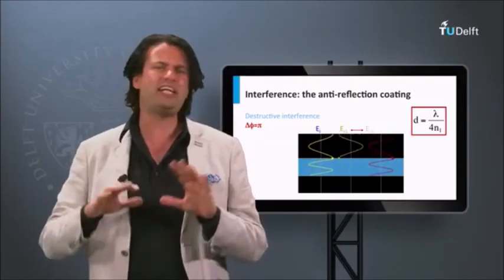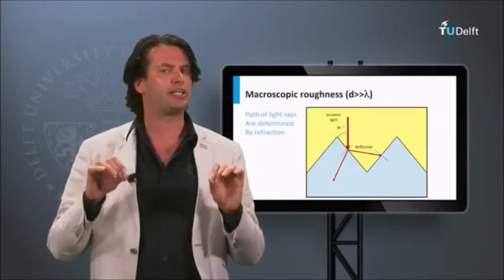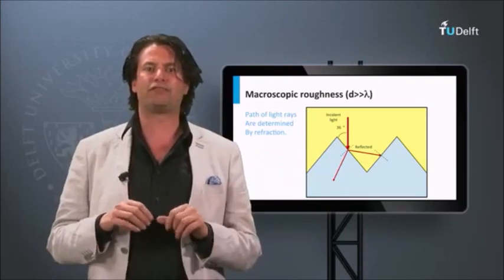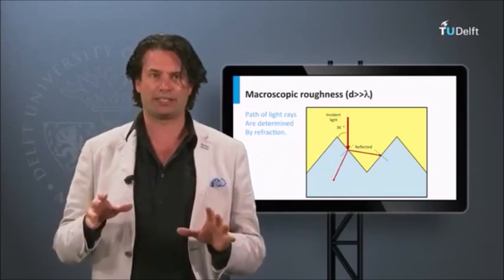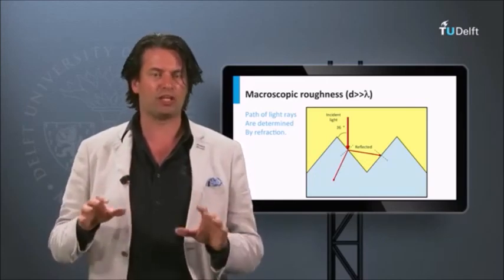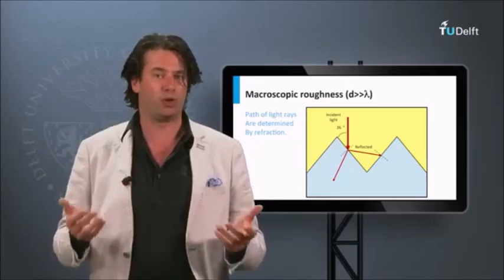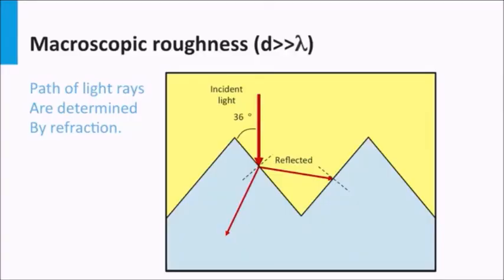A last and completely different approach for anti-reflection is using textured interfaces. The length scale of the textured features is larger than the typical wavelength of light. The reflection and transmission of the light rays are determined by the Fresnel equations and Snell's law. The texturing helps to enhance the coupling of light into the layer. For example, for light that is perpendicular incident, light that is reflected at the textured surface can be reflected at angles in which the trajectory of the light ray is incident somewhere else on the interface. Here, part of the light will be transmitted into the layer and effectively less light will be reflected in reference to a flat interface.